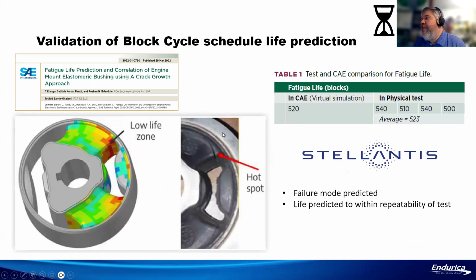Sometimes I get the question of the validation case for these, and I just wanted to throw up one example. This is one that one of our users published not too long ago, 2022, I guess, just showing that in the CAE simulation, they predicted a life of 520 repeats. This was using road loads, and in the physical test, they actually found on average about 523. So it was a very, very good correlation, both for the life and for the prediction of the location of the crack. You can see the crack right there, and you can see that's exactly where we're predicting life.